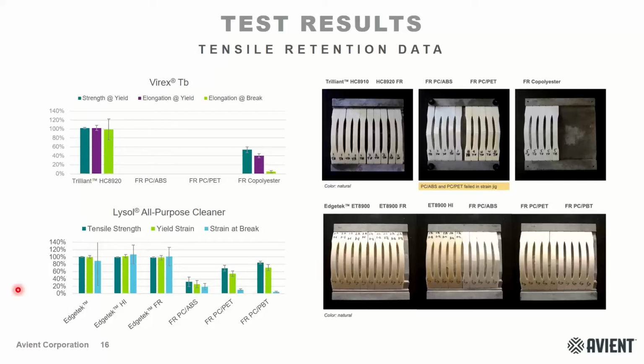If it yields, that's already kind of failed in the field, right? The elongation at break gives you a little bit more insight into whether you've seen some chain scission or whether you've had some weakening in the spot of the treatment area. And in the image on the right, what you can see when we did this test with Virex TB is that our Trilliant HC8900 series, as well as the FR copolyester, did not really exhibit signs of stress cracking.